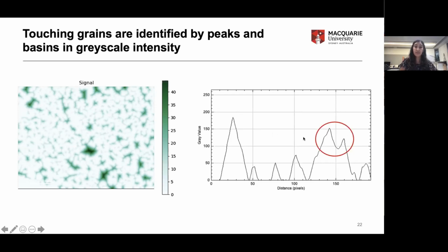By doing that, we can find out the distance to our nearest neighbor, or the nearest grain. And that's exactly what this network here is showing. Where we have these very bright central regions, that's the interior of the grain. As we fan out, the distance increases, the grayscale intensity falls, and that's where we should expect grain boundaries to be. In cases where we didn't have that grain boundary, we'd have a saddle. And we could then use the watershed algorithm again to try and cut along these saddles.